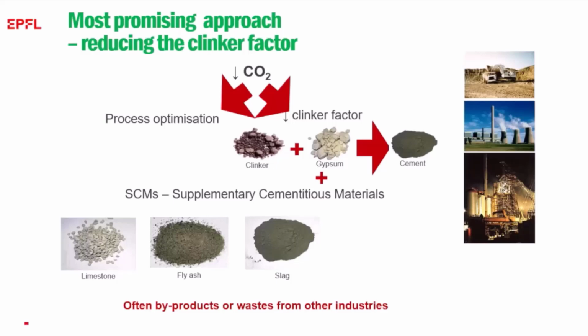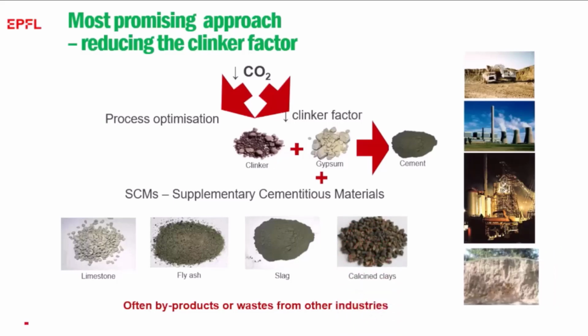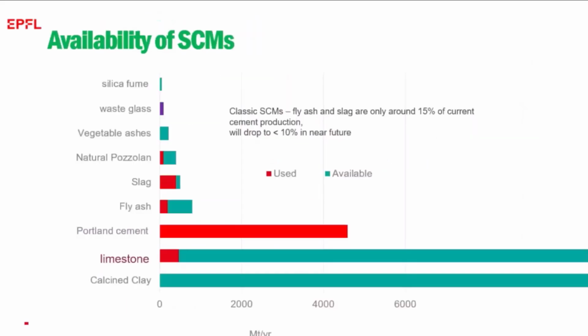And then people are looking at other slags, like steel slags, but the amounts of those are even smaller. Steel slags are typically about 2% of cement demand. So by all means, let's use these materials, but they can't take us much further than we are already. And then what we've got, which can really extend this technology, are clays, which is what I'm going to talk about. So this just shows what I already said.